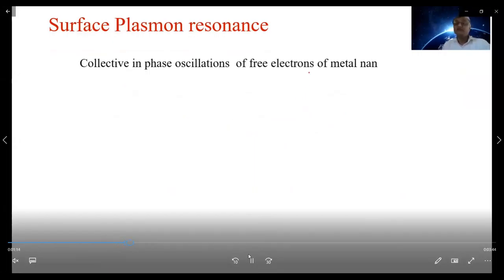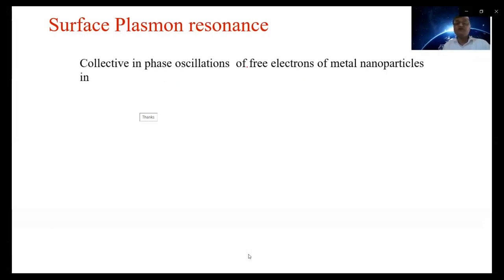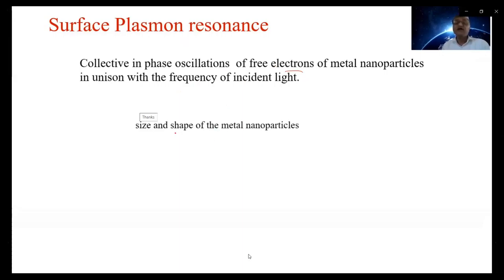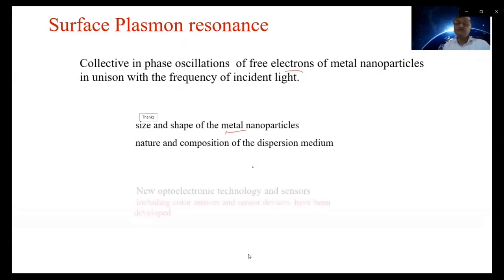Here we are studying the most important optical property of gold nanoparticles, that is the surface plasmon resonance, which finds applications in most fields like electronics, medicine, agriculture, industries, etc. Now, surface plasmon resonance is the collective in-phase oscillation of free electrons of metal nanoparticles in resonance with the frequency of incident light. SPR depends on the size and shape of the metal nanoparticles, and the nature and composition of the dispersion medium.